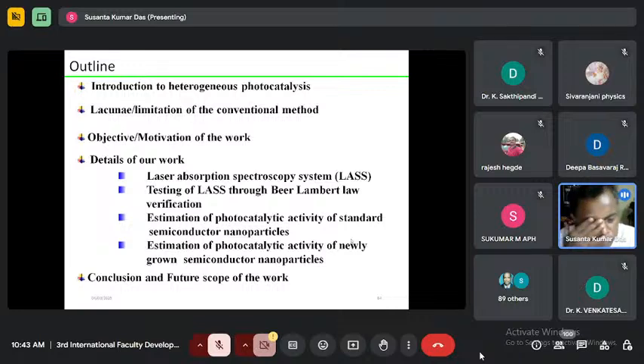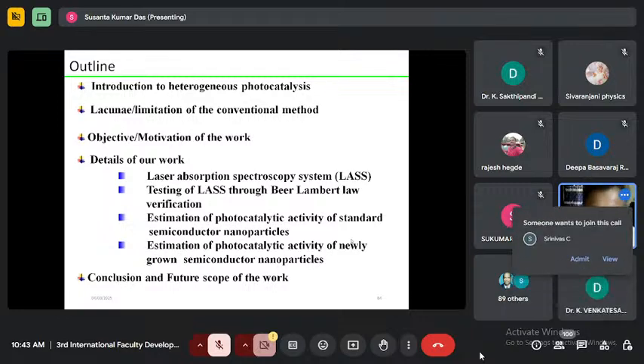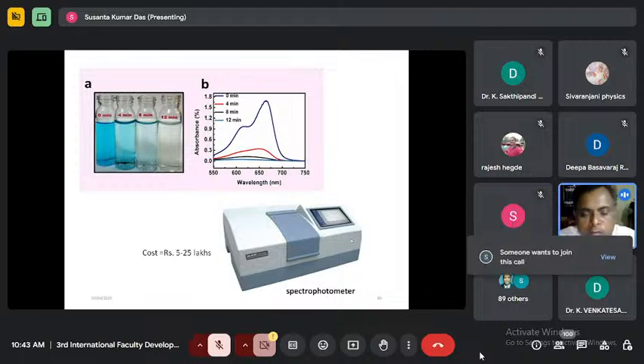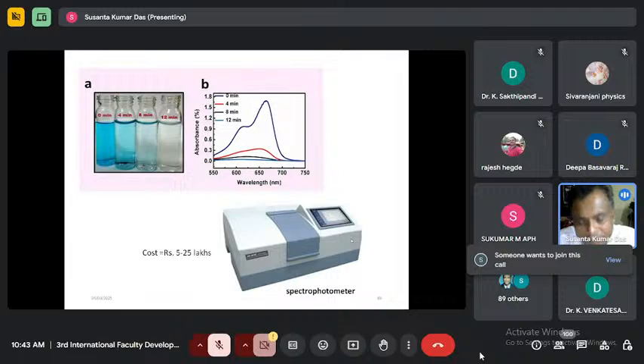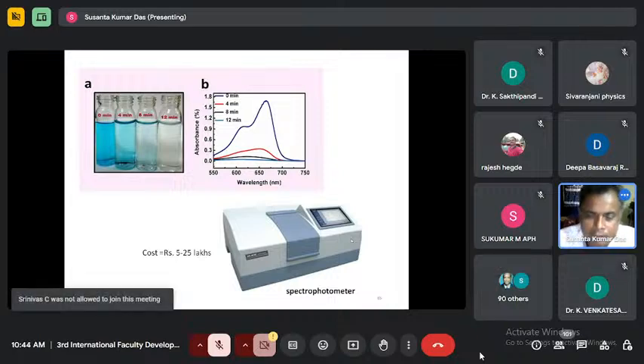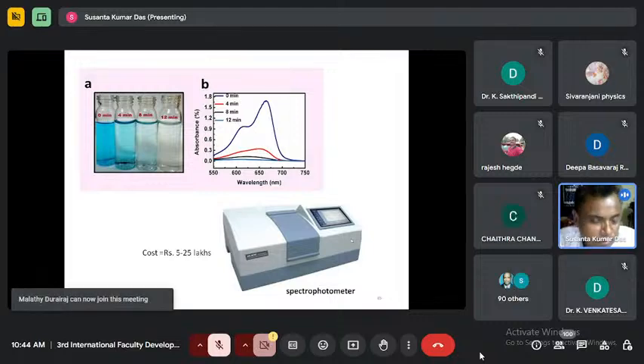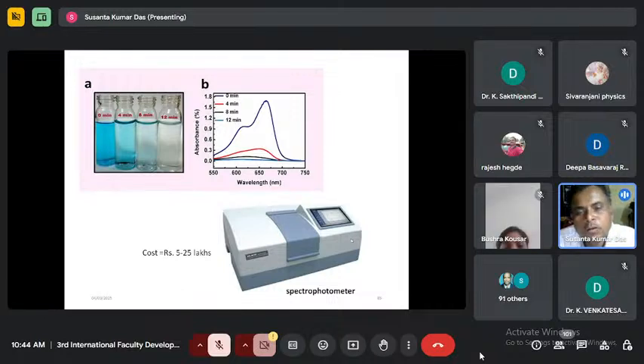The motivation was that for finding the reaction rate constant, you must go for an absorbance study, and for absorbance you must go for a spectrophotometer, which costs 5 lakhs to 25 lakhs. Earlier I was not getting access to such a system very often in the beginning step, and you have to test many times. So I tried to think of some new cost-effective systems. What I found is that the absorbance of methylene blue is at around 650 nm, which exactly matches the helium neon laser or any other red LED.